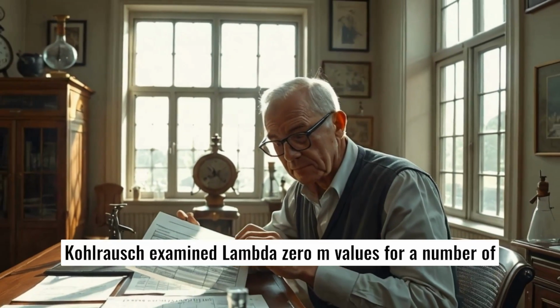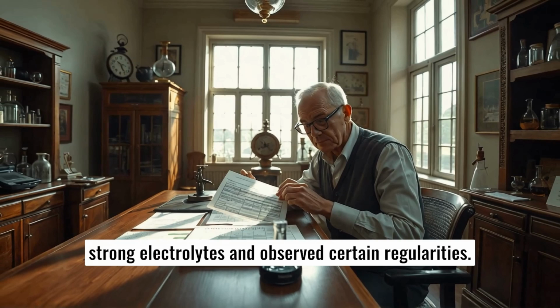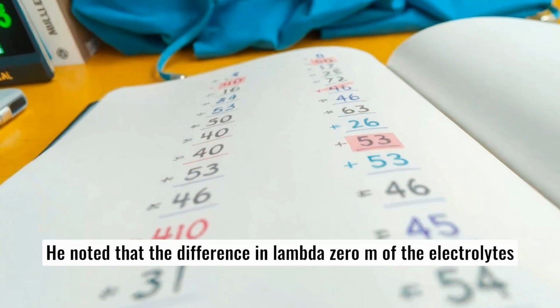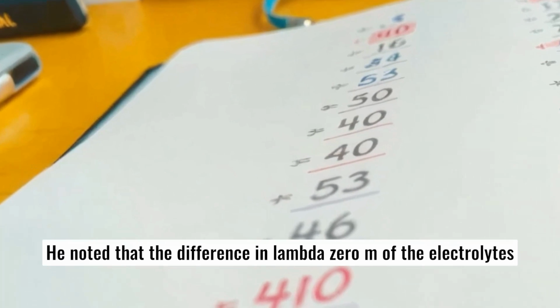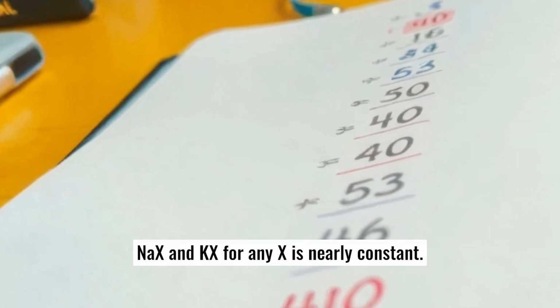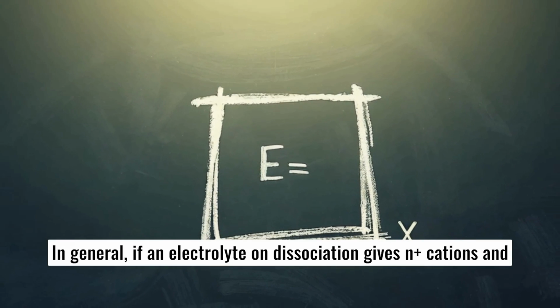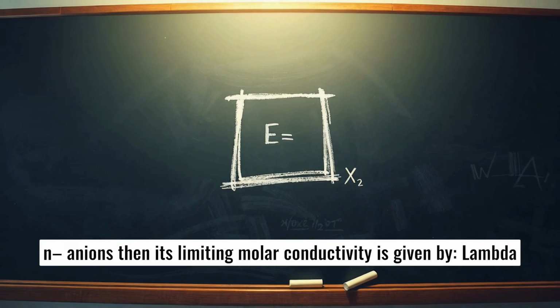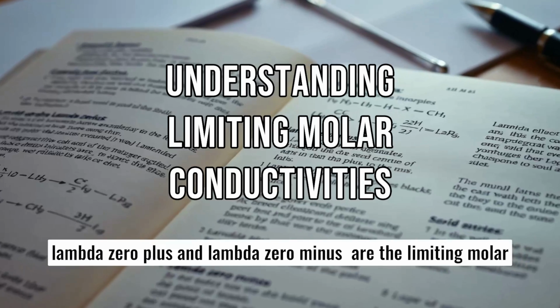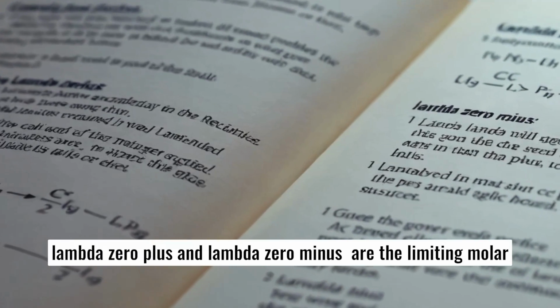For strong electrolytes, Λm increases slowly with dilution. Kohlrausch examined Λ0m values for a number of strong electrolytes and observed certain regularities. He noted that the difference in Λ0m of the electrolytes NaX and KX for any X is nearly constant. In general, if an electrolyte on dissociation gives ν plus cations and ν minus anions, then its limiting molar conductivity is given by Λ0m equals ν plus λ0 plus, added to ν minus λ0 minus. λ0 plus and λ0 minus are the limiting molar conductivities of the cation and anion respectively.